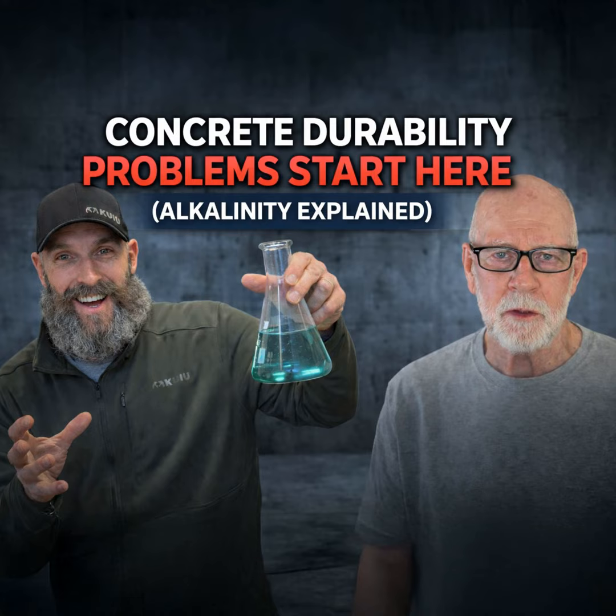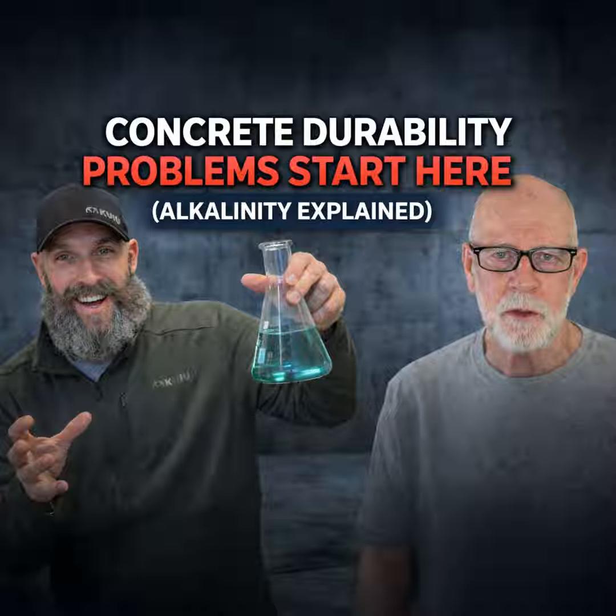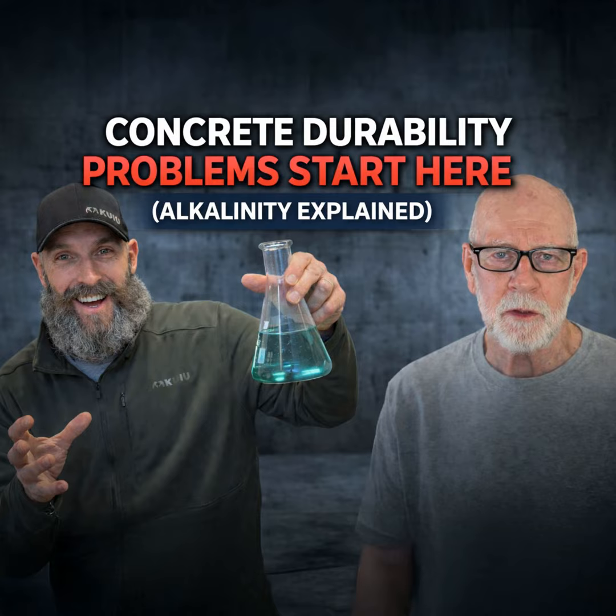Now, it doesn't do that in the center of the concrete, but it does that in the top surface, and that's where it's receiving all the damage. So why is that? That's because you've got evaporation, and it's exposed to radiant heat and the environment. Because there's a lot of contributing factors, which I'm not going to get into because that's a real deep dive. But with evaporation alone and exposure to sunlight or even light, there's an acceleration of evaporation. So the acceleration of evaporation, even with a water cure, it's not cooling the concrete properly.